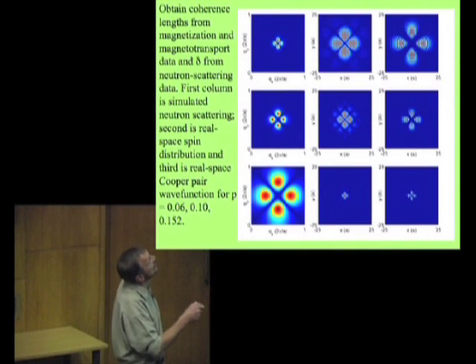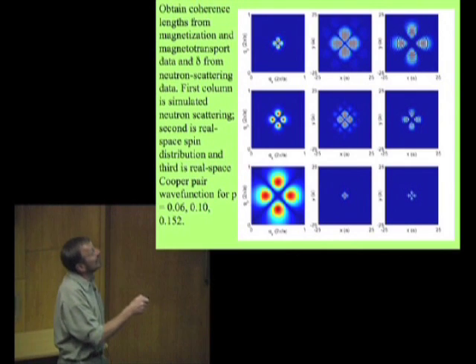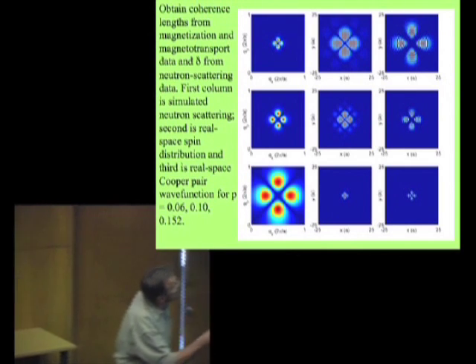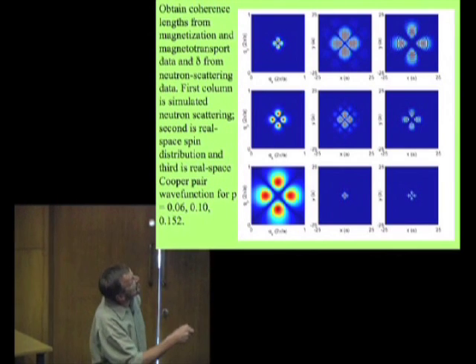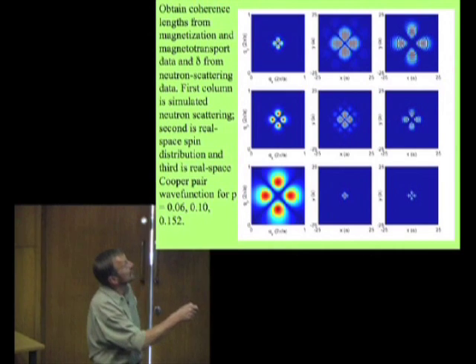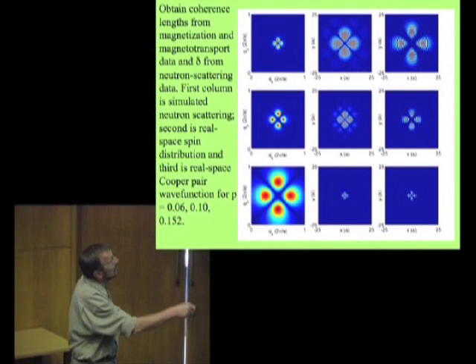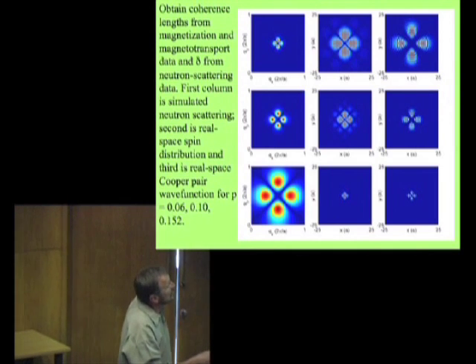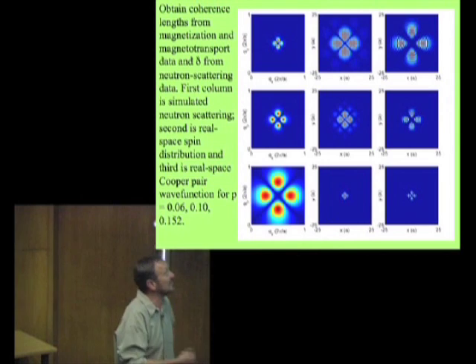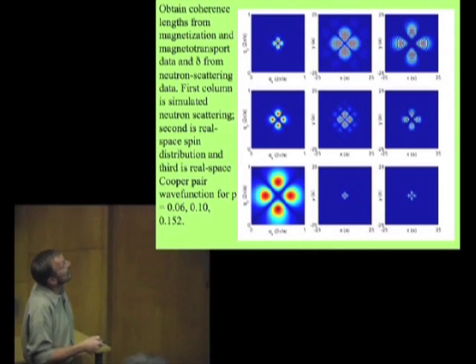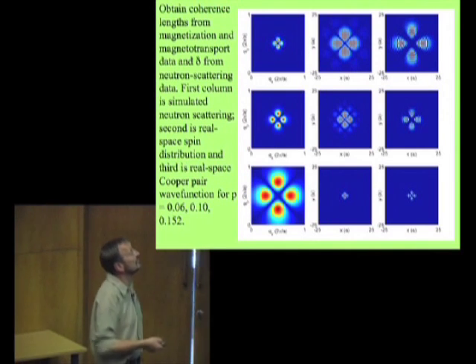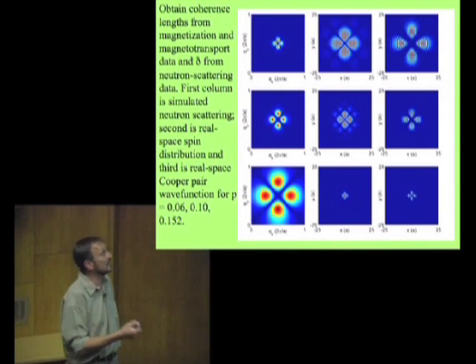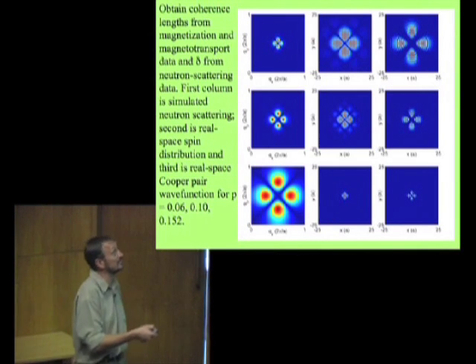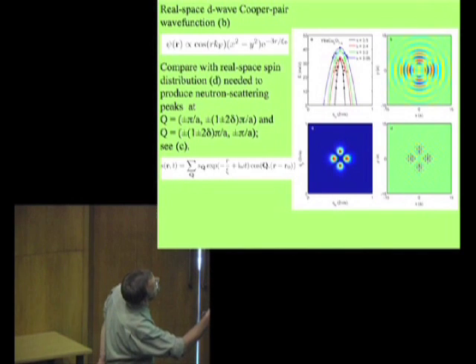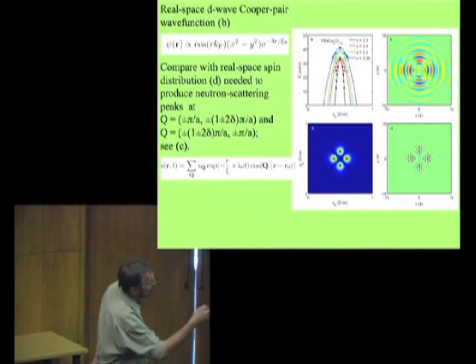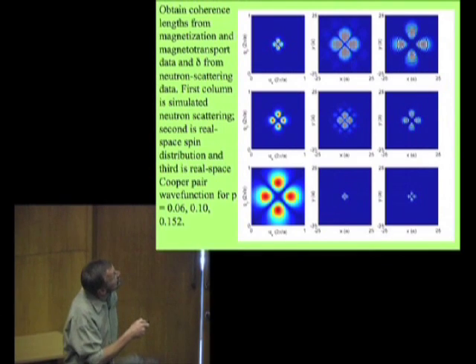So what we did was we took this parameter delta from the neutron scattering data, and we plotted out the neutron scattering susceptibility, and then we plotted out the real space spin susceptibility that gives you these scattering amplitudes here. That's the real space representation of the susceptibility that you get from neutron scattering. So notice as k space gets bigger, real space gets smaller because they have a reciprocity relationship between them. The next thing to do is to take completely independent data for the coherence length of the superconductivity, and this is measured thermodynamically from things like magnetization. The coherence length is this thing here. It comes into the Cooper pair wave function in this exponential term here. And this is for different hole dopings.